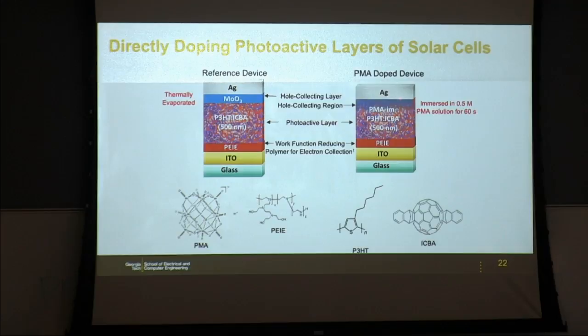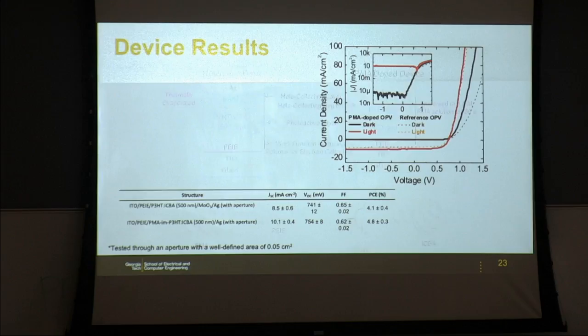Okay? And because this is heavily P-doped, has a high work function, it makes it an efficient hole collecting layer for the solar cell. And so we're able to do that, and here's the current voltage characteristic of these devices in the dark and under illumination. And you see the corresponding power conversion efficiency of these solar cells, close to 5%, which with P3HT is really